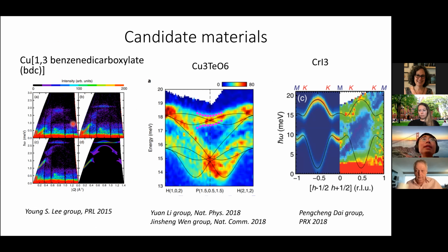I think both of them are stable. But for chromium triiodide, there is some issue where as you increase the number of layers, there seems to be a transition between the few-layer case and the many-layer case. The many-layer case seems to be a ferromagnet, but the few-layer case seems to be antiferromagnet, so something happened there - it could be structural or other things, but chemically it's stable, I think.